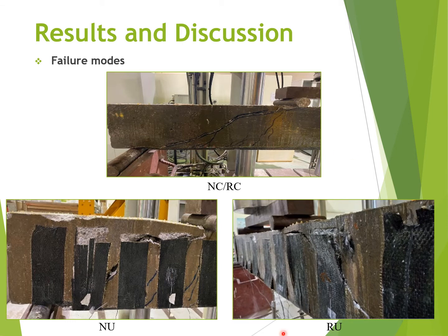On the other hand, the specimens NU and RU primarily failed by the debonding of the U-wraps, as you can see in these two figures. The failure in the strengthened specimens was initiated by the formation of shear cracks, and as the load increased, the cracks widened and the bond between the U-wraps and concrete was lost, which consequently resulted in the debonding of the U-wrapped laminates. It was observed that the U-wraps that debonded from the concrete were the ones that intersected the critical shear crack. Mainly the middle three U-wraps were the ones that debonded.